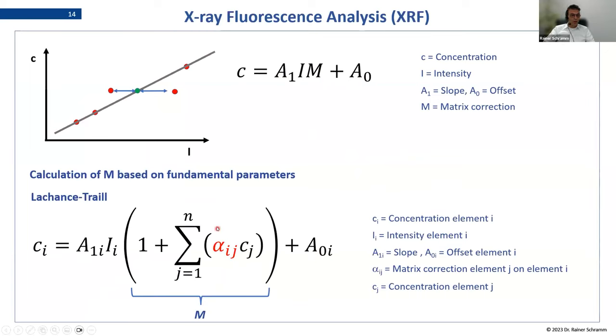And there would be the Lachance-Traill model. And instead of our coefficient a_ij, now I call it alpha_ij. That's the only difference from the last formula, because you might know it better as alpha correction models. And this is why we just changed the term a bit. But it's exactly the same formula as before, but now with the idea that our coefficient is not calculated by standard materials, this time the coefficient is calculated from tables.